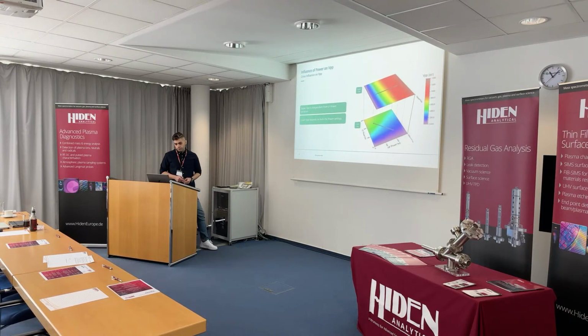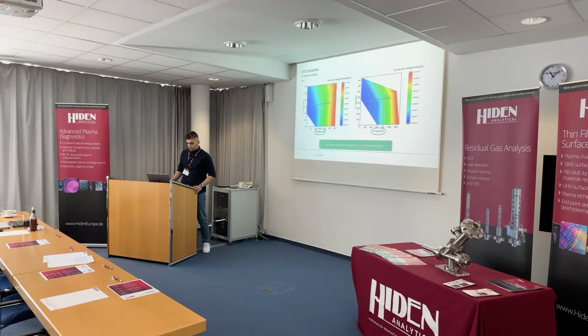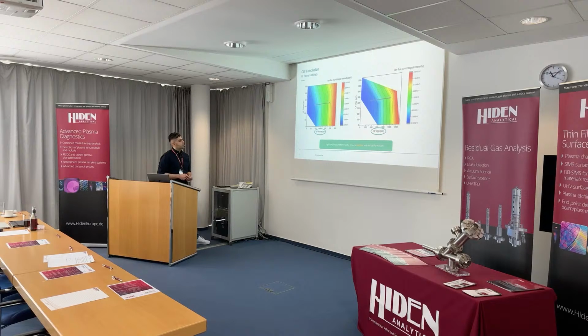And this is the influence of power on VPP. So when we change the HF power and LF power, the upper VPP is just influenced by HF power, and the lower VPP is influenced by both HF power and LF power. And this is the conclusion for continuous wave. You see the HF power and LF power influence on ion flux. So ion flux is mostly influenced by HF power, and you see the HF VPP, which is the product of HF power, only corresponds to higher frequency.